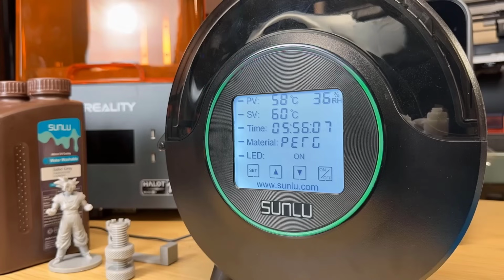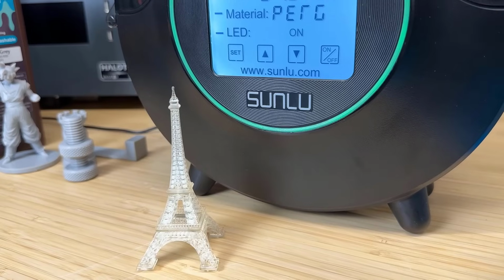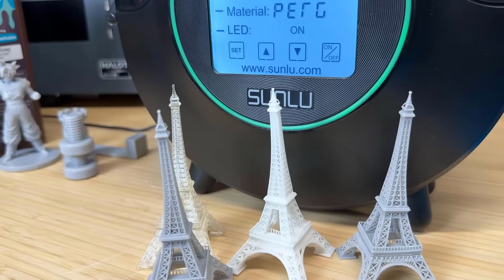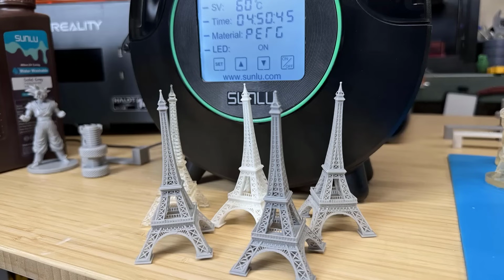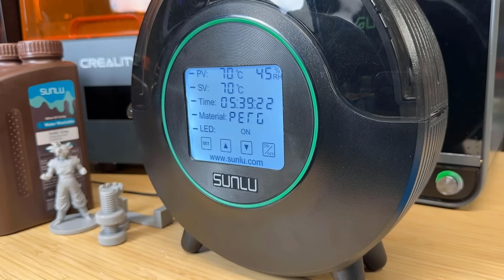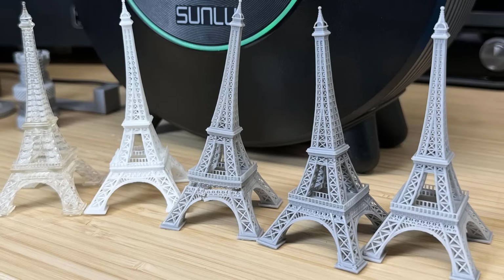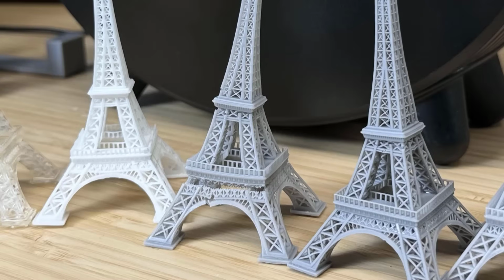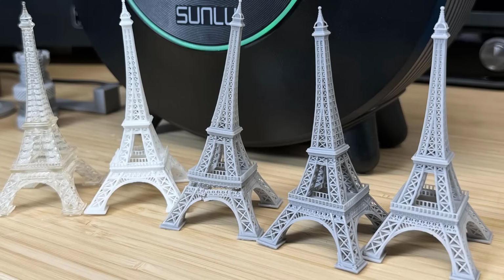I will then increase the temperature to 60 degrees Celsius and run it for another hour. The models still look fine, with no signs of cracking or melting. Finally, I will set the filament dryer to its maximum temperature of 70 degrees Celsius. At this point, the standard resin began to break. The bottom and neck of the tower showed visible cracking. However, all the other resins remained intact.